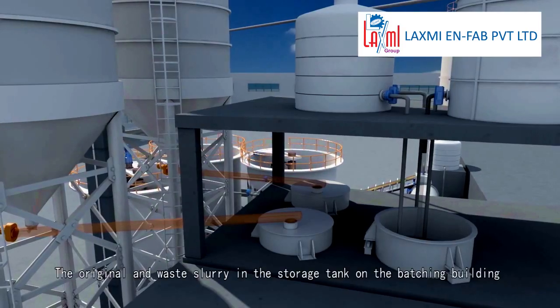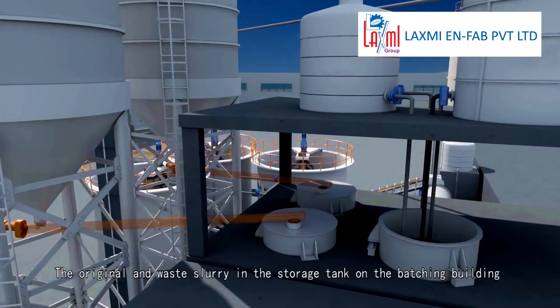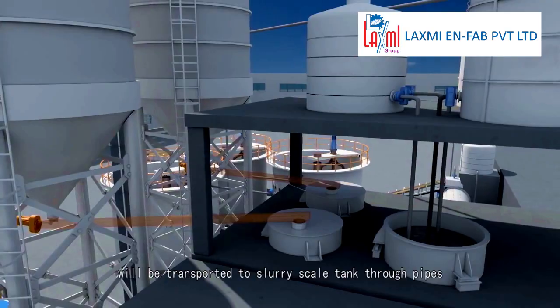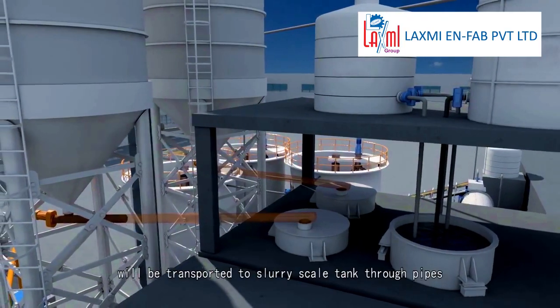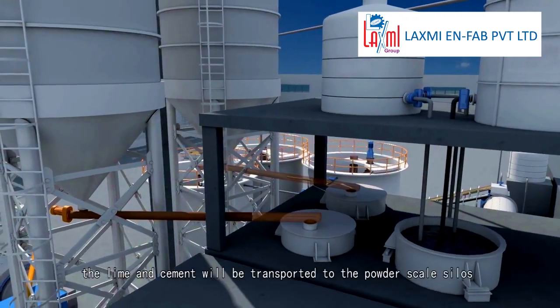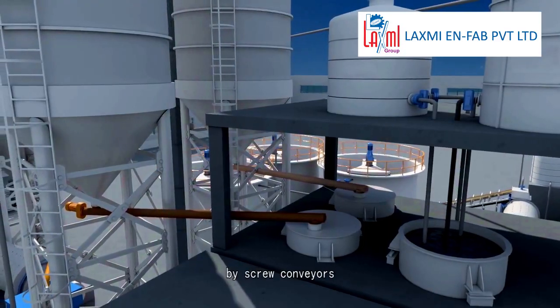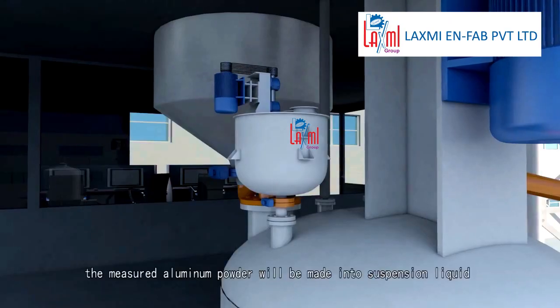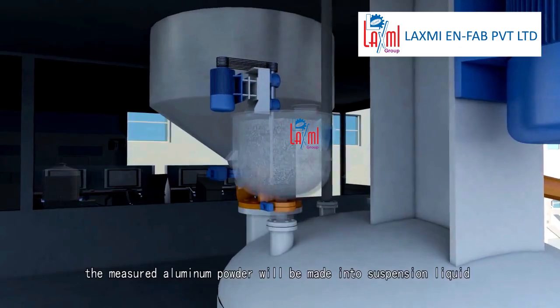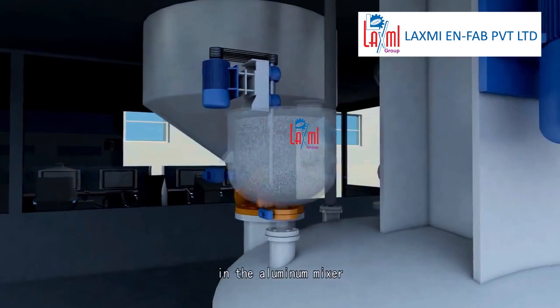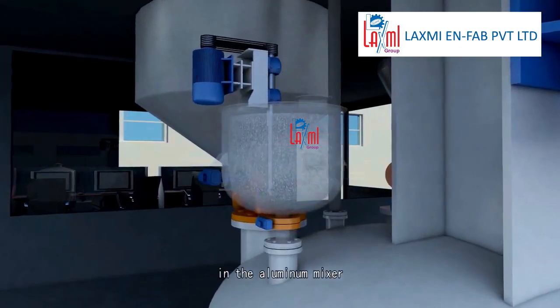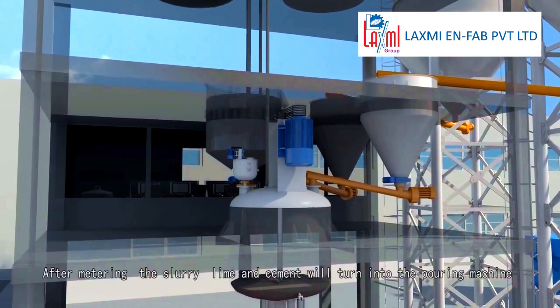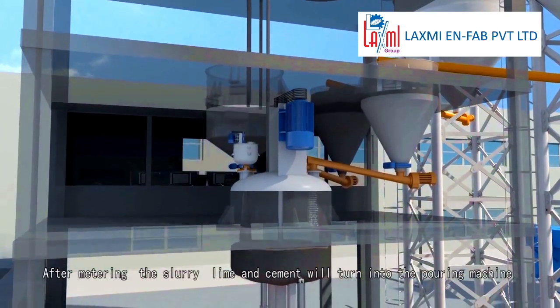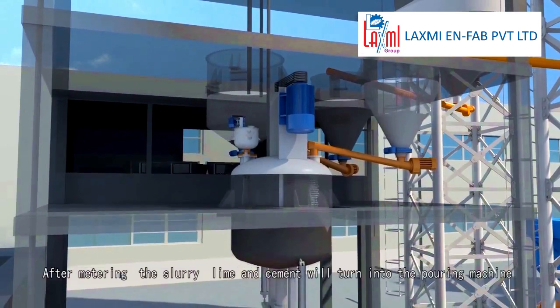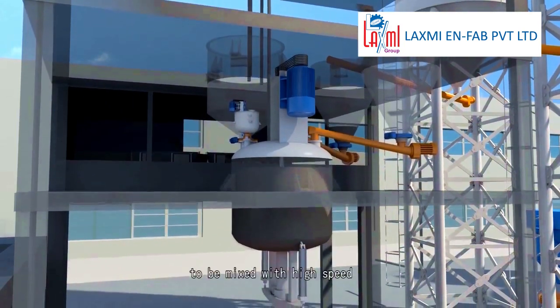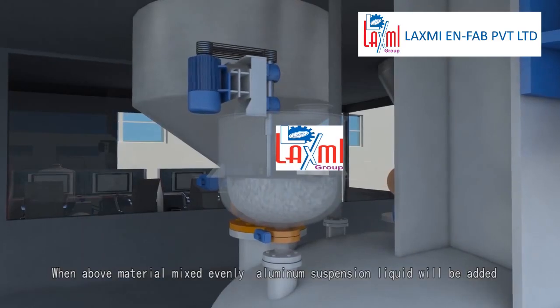The original and waste slurry in the storage tank on the batching building will be transported to slurry scale tank through pipes. The lime and cement will be transported to the powder scale silos by screw conveyors. The measured aluminum powder will be made into suspension liquid in the aluminum mixer. After metering, the slurry, lime, and cement will turn into the pouring machine to be mixed with high speed. Aluminum suspension liquid will be added.